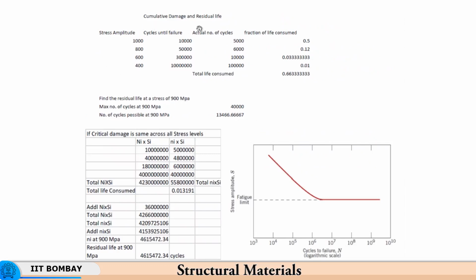Now, we have a situation where we have a rotating shaft which is subjected to bending moment, and I have loaded it to a certain amount of stress for a certain number of cycles. Okay. So, this is the actual number of cycles. If it is 1000 newtons, then the actual number of cycles is 5000 cycles. 800 newtons I have loaded it up to 6000 cycles. At 600 newtons I have loaded to 10,000 cycles. 400 newtons remained for 1 lakh cycles. So, basically this has been the loading schedule which I have had.